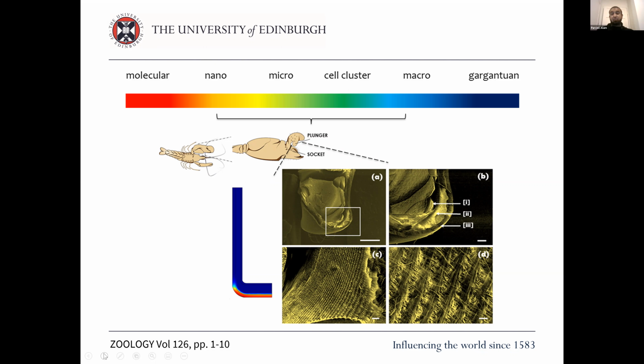But basically, we cleaved these plungers, and what we found was that they are composites. They're sandwich composites. So you've got a bottom layer, an outer layer, and an inner layer that are made of a composite itself, which is calcium carbonate bonded by proteins and polysaccharide type matrices.